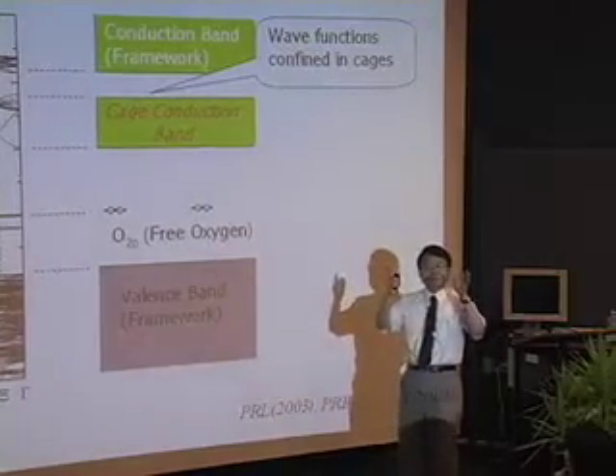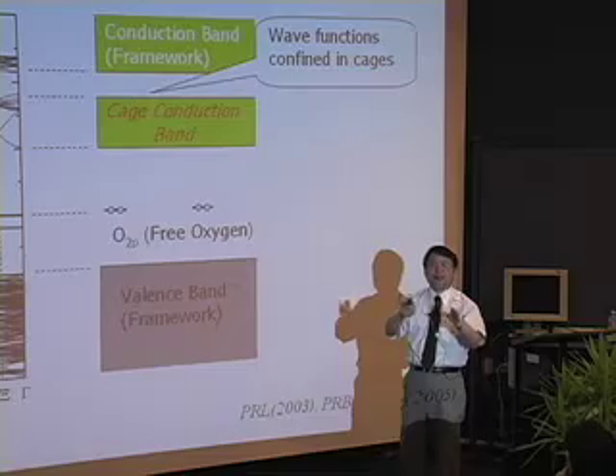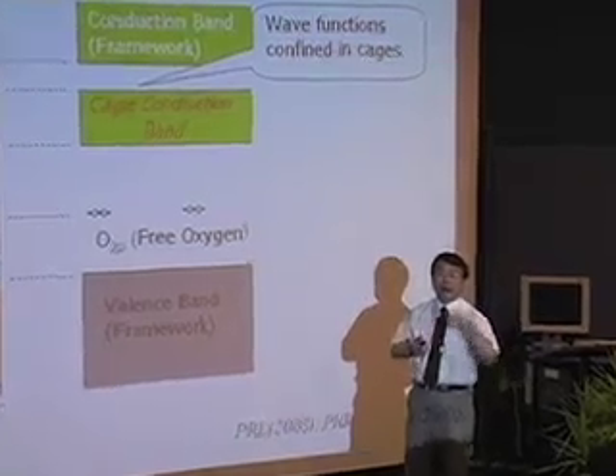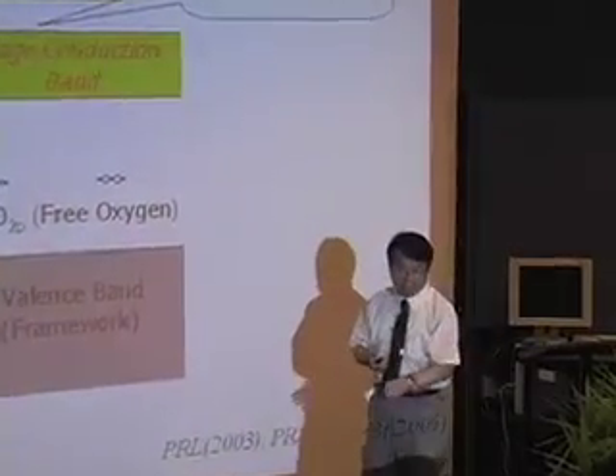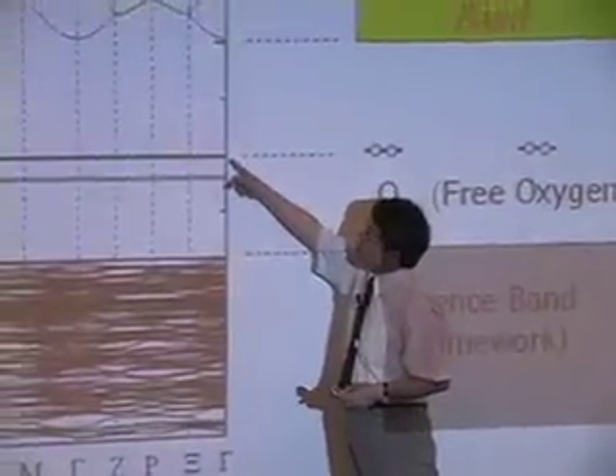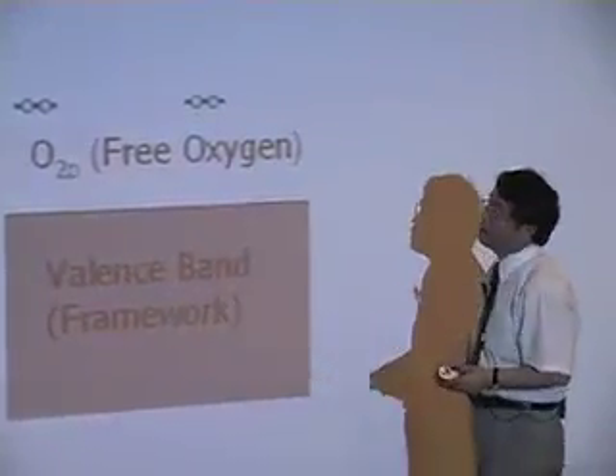The cage structure is positively charged, so by trapping an electron the cage structure becomes stable. Then its level comes from oxygen 2p of the free oxygen ion. The oxygen ion is loosely bound, that's why this 2p level is a little bit high.